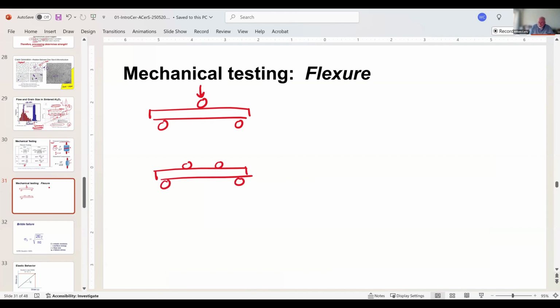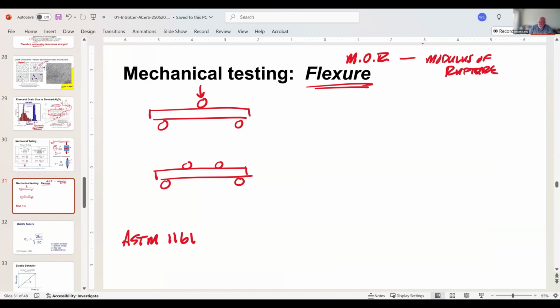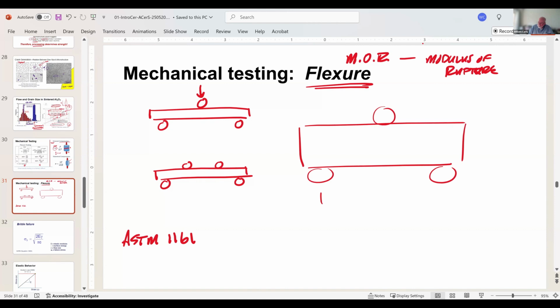Okay, and there's a specification, ASTM C1161, which is the specification for flexure testing. Okay, this used to be called modulus of rupture. And it was designed to get around an interesting problem, and that is tension. So in this bar, I've got my support down here, and my support here, and my support here. And by the way, this distance here should be 8 times D, a minimum of 8 times D, okay? And this is then D, depth.